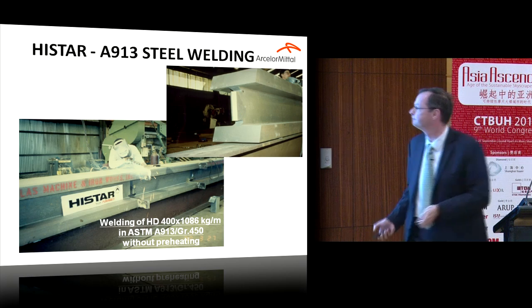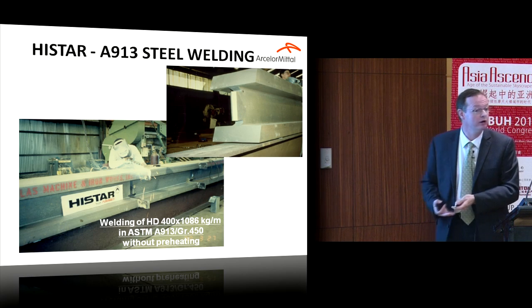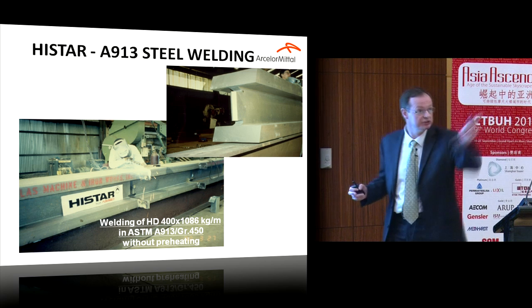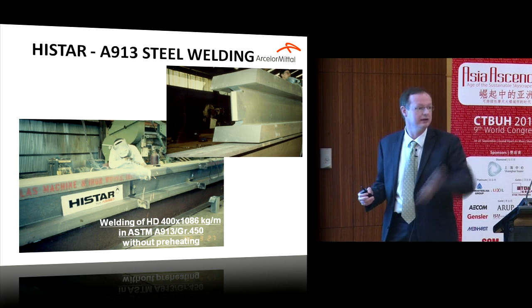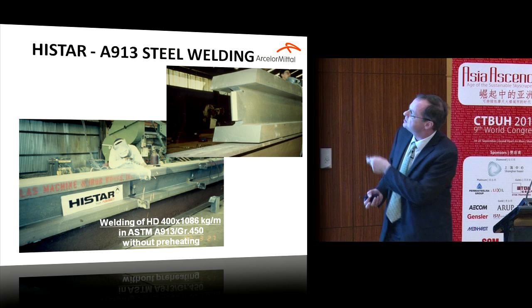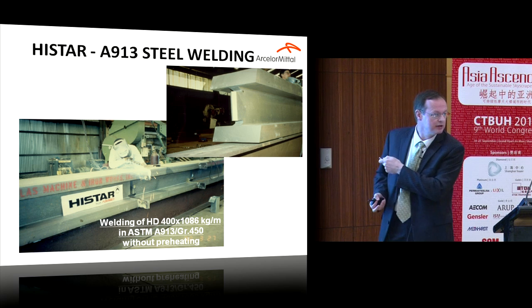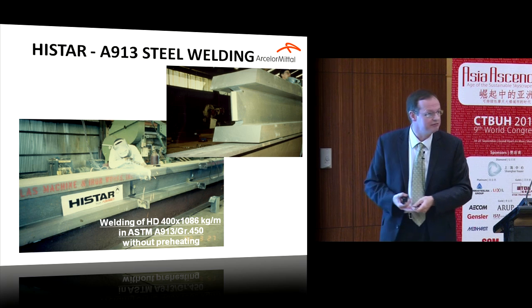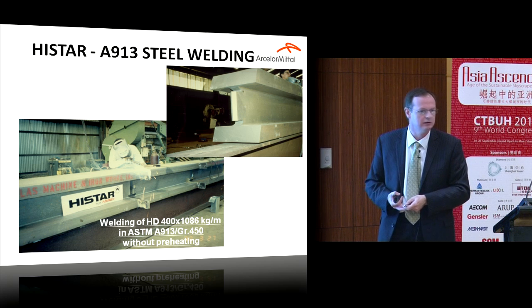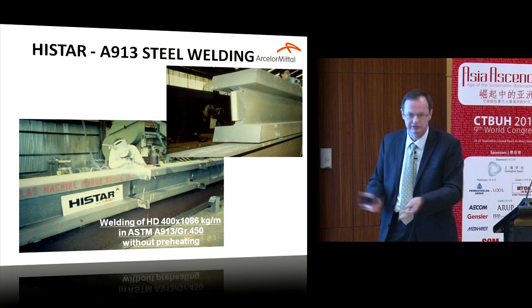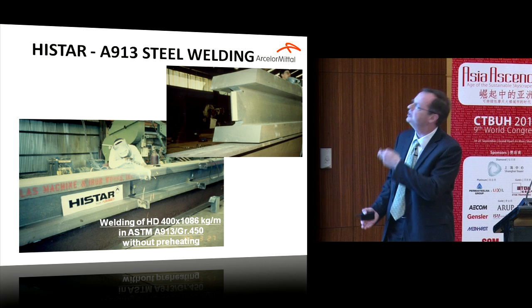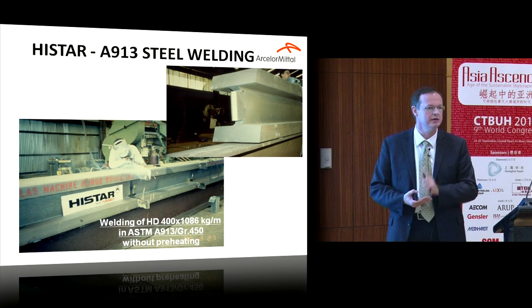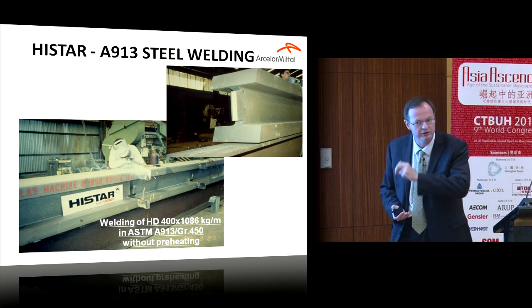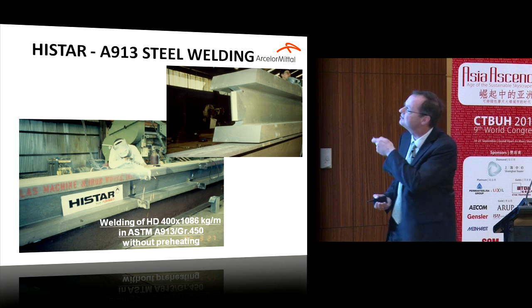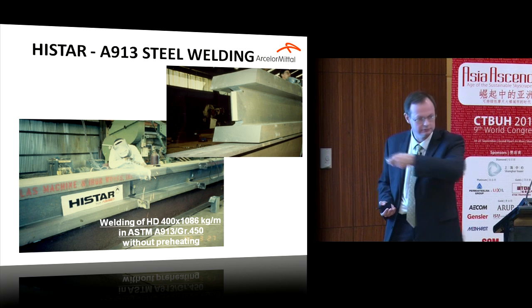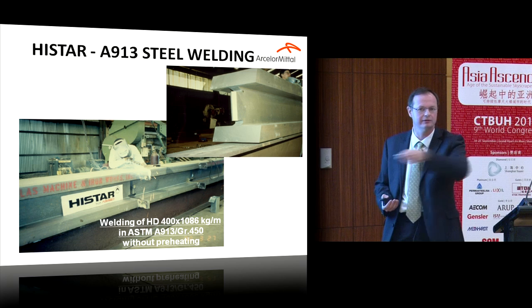By using the quenching and self-tempering process, we can produce high-strength steel with very good ductility and very good weldability. This is an example of a splice in a jumbo, which I think is what we have supplied in this building. It is 125 millimeters thick. If you use a normal 355 megapascal steel, or Chinese plates available here, you must preheat to 110 degrees before the first pass. It takes about 5 hours with a torch, just doing that.